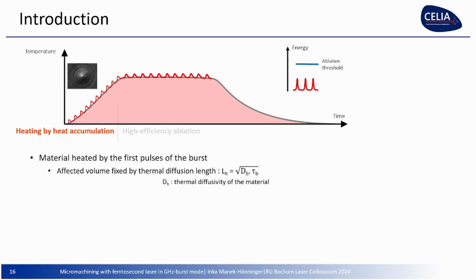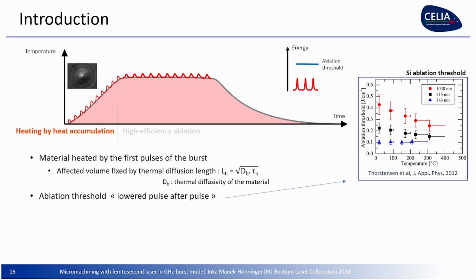Do we want to avoid heat for femtosecond micromachining? Yes, but if you can accumulate heat in a wanted way, in a way that you can choose how to use it, then it can be beneficial. Our group showed that when you're heating, the ablation threshold goes down. Well, I would rather say it's like going up a mountain: starting from sea level, the way is much higher than if you are already at a base camp, which is quite high. So the ablation threshold is not really lower, but you are much closer to it, and the difference gets lower.